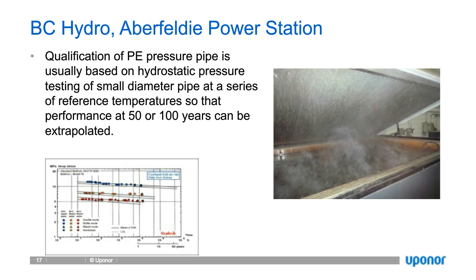If one does sufficient testing at elevated temperatures, it would produce failures that are not ductile but brittle, slit-like failures. And testing at multiple elevated temperatures can be extrapolated to determine that we will not suffer slow crack growth failure with polyethylene resins. Please note that the plots you're seeing here are log-log plots. Small decreases in stress give rise to very significant increases in the time to failure. So Uponor and its predecessor company have conducted a significant number of hydrostatic pressure tests on various wall geometries of Weholite. But given the size of the sample, we clearly cannot conduct as many tests as could be conducted for solid wall pipe, and we cannot rely only on hydrostatic pressure testing.